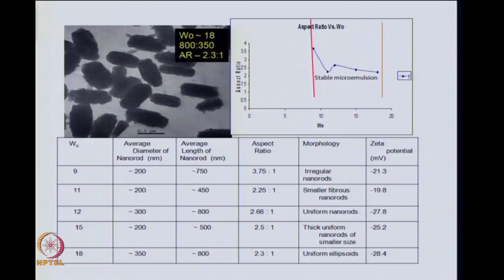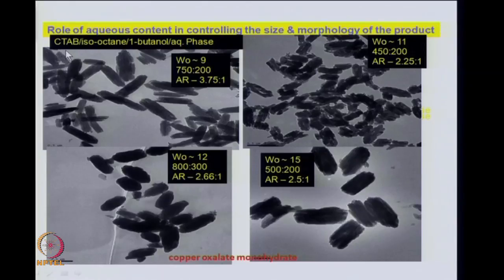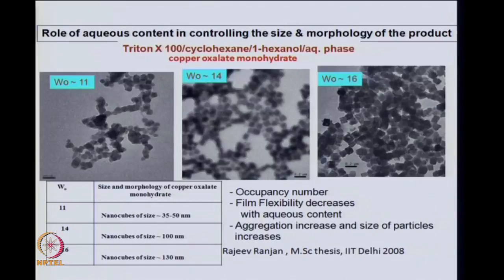In the earlier case, we had taken CTAB as the surfactant, which gives rise to anisotropic structures, and in these anisotropic structures, as we increase W0, the aspect ratio continues to decrease, which in a way tells you that the size of the spherical particles or the cubic type of particles will increase as the W0 parameter increases, whereas the anisotropy will decrease as the W0 parameter increases. So, in a more constrained reactor, in a more constrained reverse micelle, the anisotropy is higher.